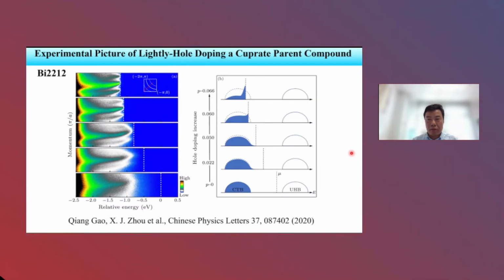Also, we did the work to dope the Mott insulator by holes, by substituting holes. But because of time limit, I'm not going to talk about it in detail. But in this case, we use bismuth 2212, starting from about 6.6% doping. Then we also dope electrons on top of it to reduce the doping to 0. So we start from hole doping about 6.6%, we put the electrons on top of it to reduce the doping level to 0, and we can also establish the experimental picture of the doping-dependent compound. And you can really see that in this case it's quite different. You cannot see this region because the chemical potential is here. Okay, it's a very different evolution picture compared with the electron doping case.